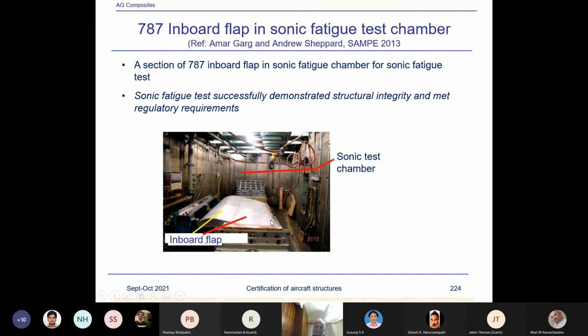There were lots of strain gauges. There were some damages also, like BVIDs, to demonstrate that BVID does not become detrimental due to the sonic fatigue spectrum. Trailing edge fasteners: the demonstration had to be done for the trailing edge fasteners because in the 787 design, trailing edge fasteners are very critical. And the sonic fatigue test successfully demonstrated structural integrity met regulatory requirements.